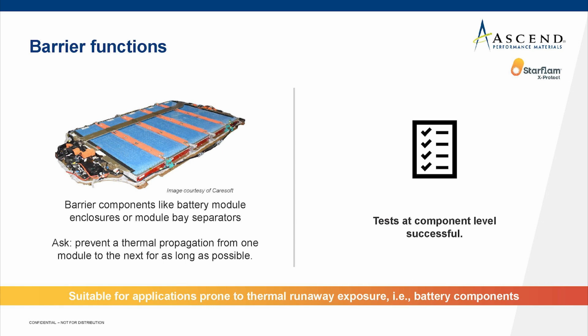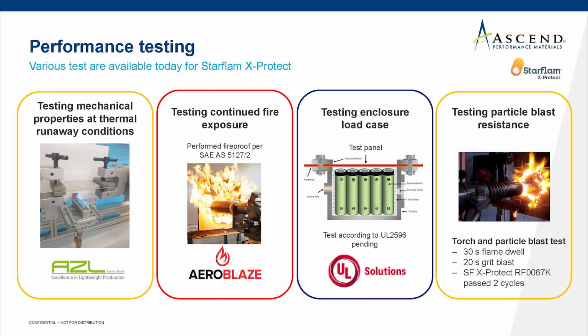So in case of a thermal event, this event does not propagate from one module bay to the next. These barriers can be produced, for example, out of Starflam X Protect, and we already went through some successful component level tests. That means we produced barriers and exposed them to a torch. From our perspective, the next level of testing would be to go to an actual pack and see whether that propagation can be really stopped. So this is also a matter of thermal transition and heat transition. I'm really looking forward to those kinds of tests. This concludes what we were presenting today about thermal runaway as such.